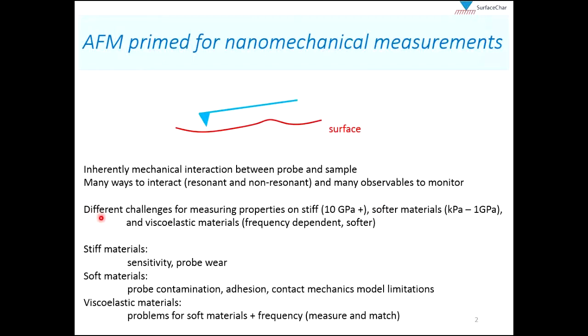But in terms of conducting nanomechanical measurements, AFM faces different challenges for measuring properties on samples that are stiff, let's say 10 gigapascals or higher, as softer materials in the kilopascal to gigapascal range, and viscoelastic materials, materials that have a frequency dependence to their elastic properties.